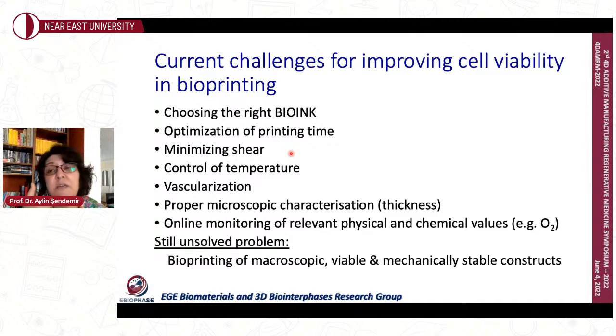So we do have a lot of different approaches to improve cell viability, but choosing the right bioink, that is not easy, that's not trivial. A lot of my students, for example, think that the first time they try in the laboratory, they will succeed. No, that's not the case. It needs quite a lot of time and effort to optimize bioink concentration. Optimization of not only the ink, but the printing time, minimizing the shear, so printing parameters, control of temperature, control of vascularization afterwards. Proper microscopic characterization, again, the thickness or pore structure.